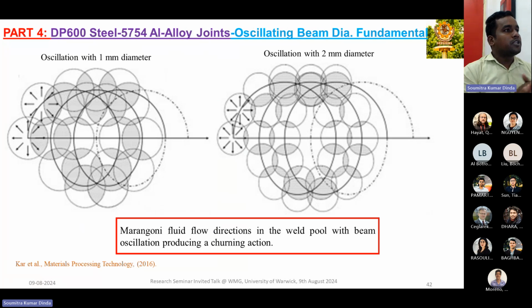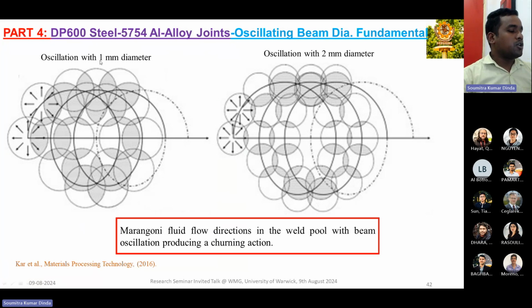So what is happening then in case of joint 2 and joint 3? Because both cases are oscillating beam, right? But this one is 1 millimeter and the third one is 2 millimeter. So when we are increasing the oscillation diameter, there may be a chance that it exceeds the limiting overlapping factor, or limiting overlapping area. If we choose say 1.5 or 1.75 millimeter diameter, then maybe we get more superior property, but 2 millimeter exceeds the limiting value of the overlapping. That is the reason why in case of joint 3 we are getting the worse mechanical property, or very high welding defects compared to joint 1 or joint 2.